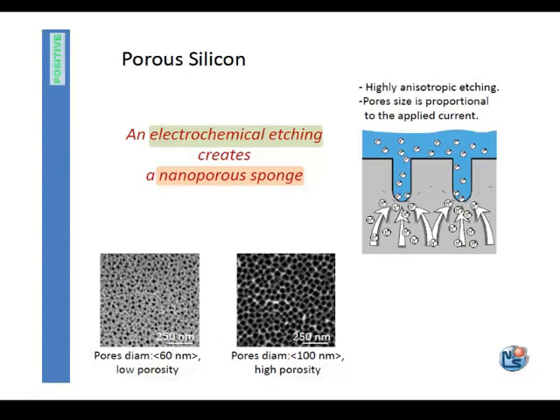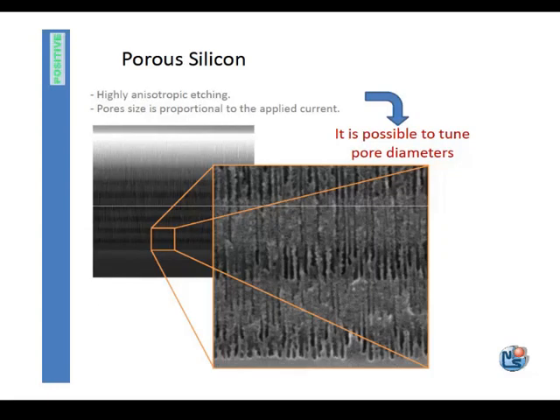These are two SEM images that show two different samples with 60 and 100 nanometer average pore size and different porosity. The structure is highly anisotropic. Pores are straight channels that do not interconnect with each other. And the pore size is proportional to the applied current. That's why porous silicon became